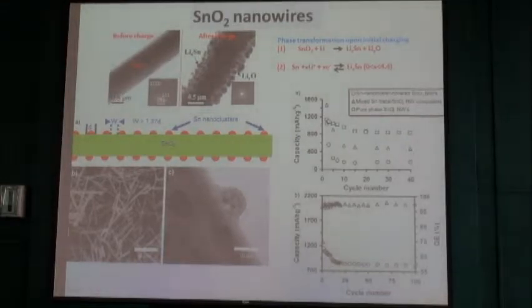So this is one example of what we did. Actually, we have a patent on this discovery. You can see if I use tin dioxide nanowires here, this is a very nice nanowire, highly crystalline. But if I use lithium, eventually it is going to dissipate. So what we did was, in the nanowire, we added small metal clusters, but the important thing is the separation between these clusters has to be larger than their diameter.